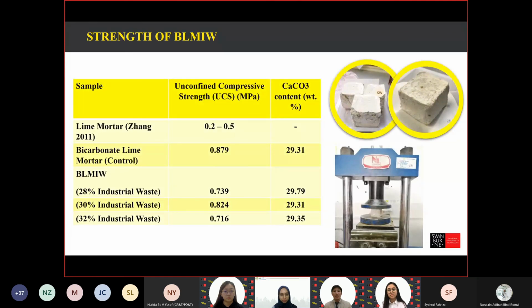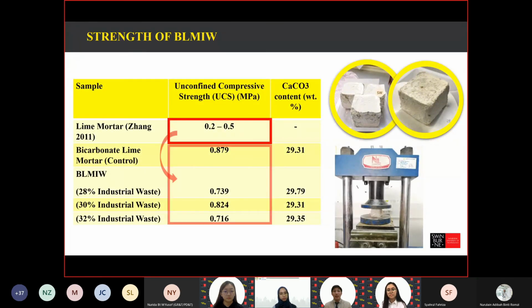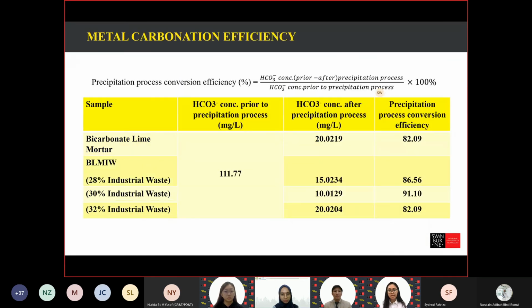Next, we look at the strength of bicarbonate lime mortar with industrial waste. It is shown that typical lime mortar has an inferior unconfined compressive strength compared to bicarbonate lime mortars. This is due to its slow carbonation of calcium hydroxide with air to form calcium carbonate. Bicarbonate lime mortars exhibit higher strength because of the use of bicarbonate solution, which provides both calcium and carbon source for its precipitation. Bicarbonate lime mortar with 30% industrial waste shows a comparable strength to bicarbonate lime mortar, as both samples gave similar CaCO3 content.